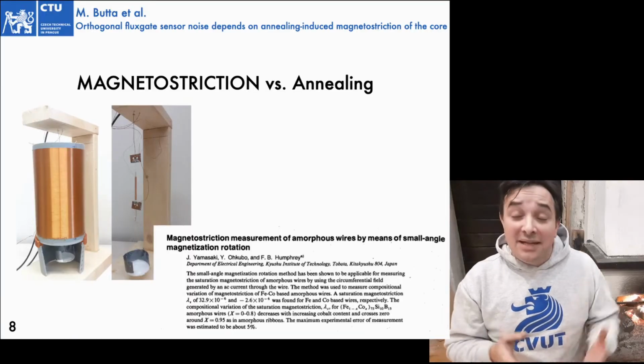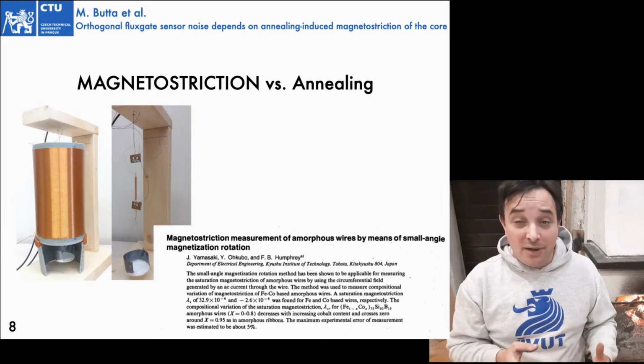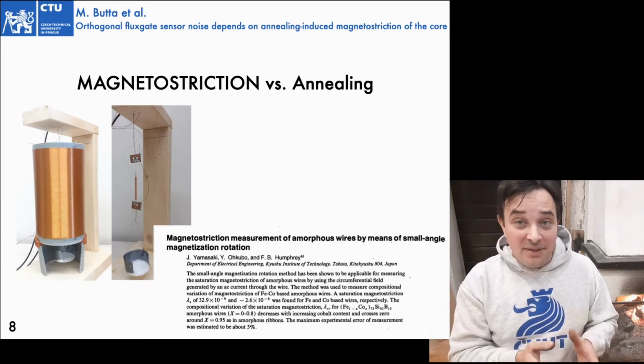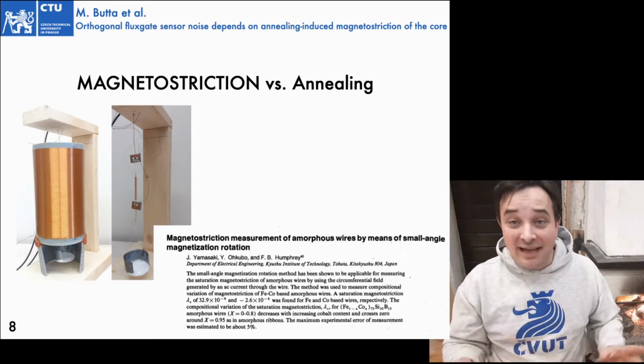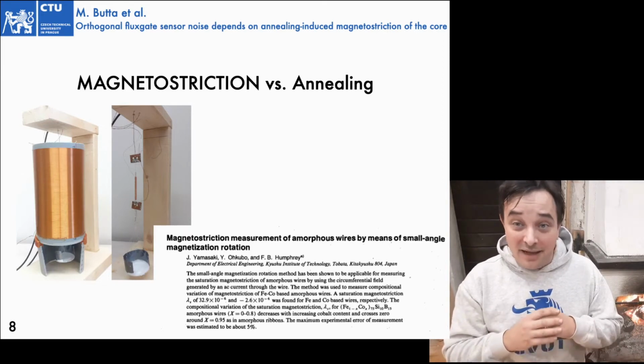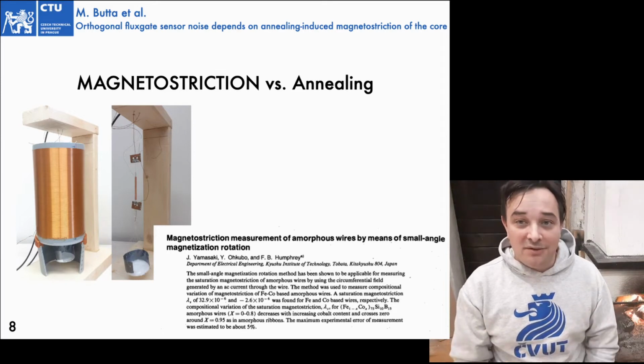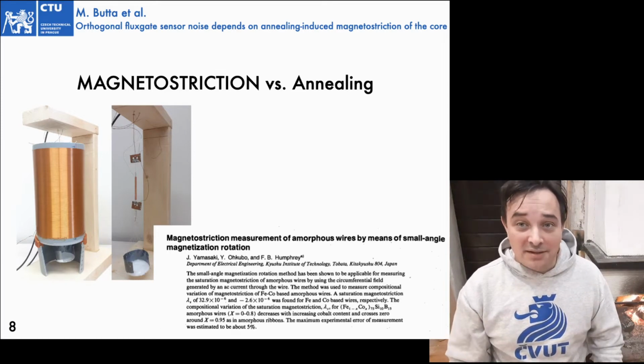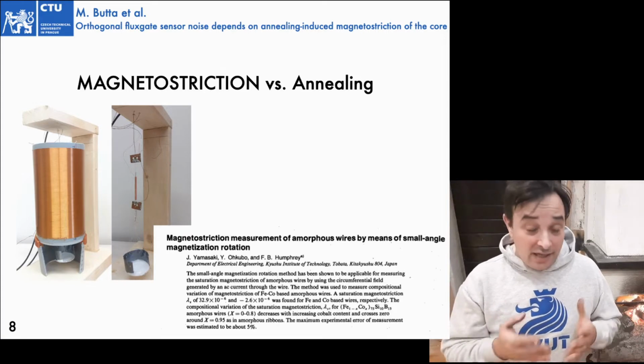We have only one thing to do, to measure the magnetostriction. And how do you measure the magnetostriction of a microwire? Keep in mind that these wires that we use for our sensors have a diameter of 120 micrometers, something like that. Well, the best way to measure the magnetostriction of a microwire is to use the classical method of the small angle rotation. Just read this paper, it's a classic, it's fantastic, and you can achieve really precise measurement of the magnetostriction of this kind of wires, even if the magnetostriction is very low, like in our case.